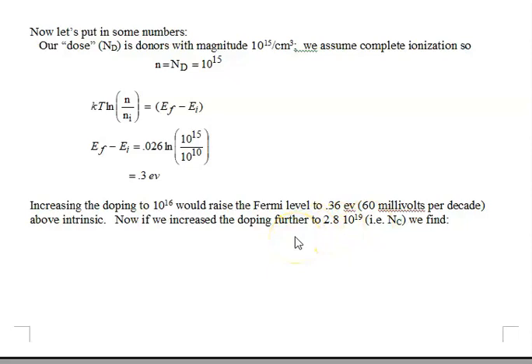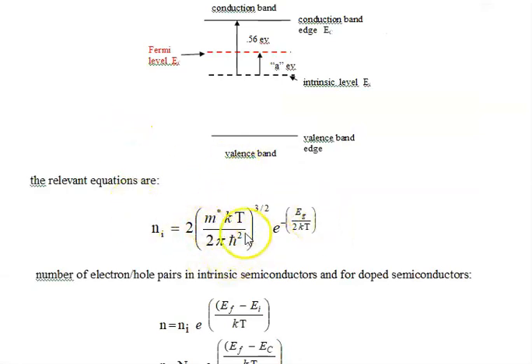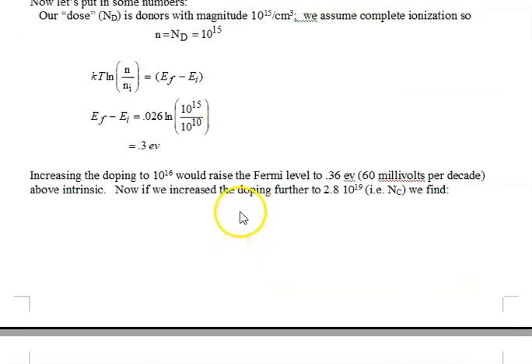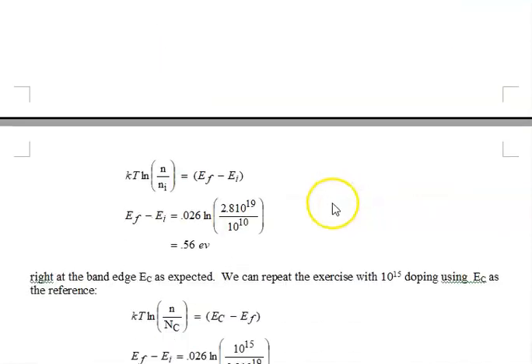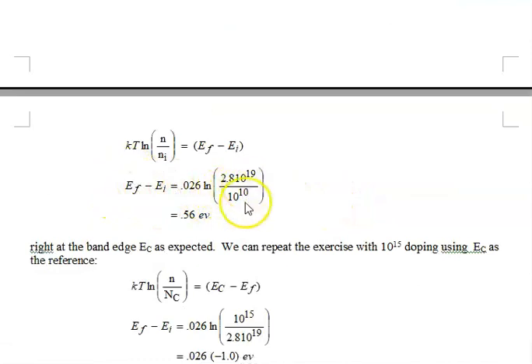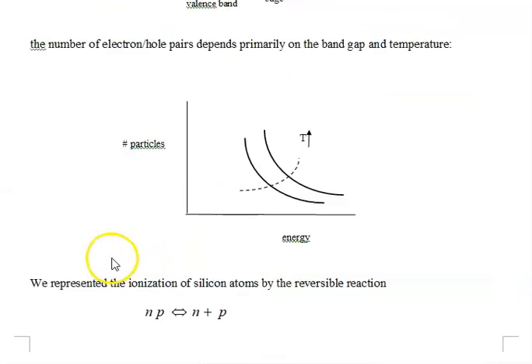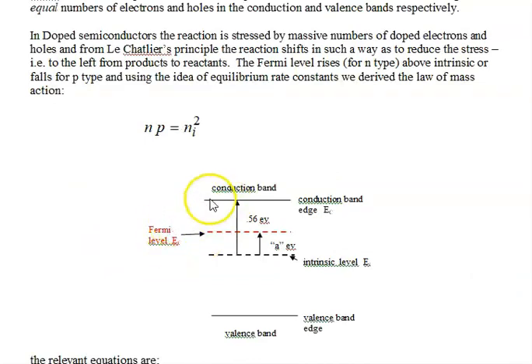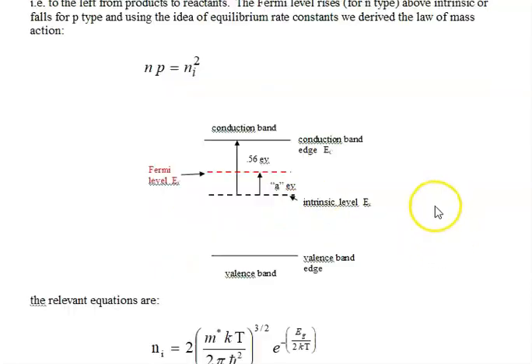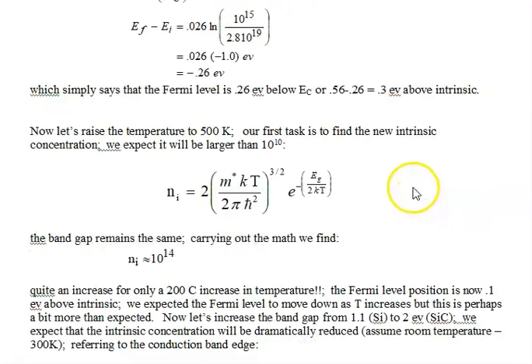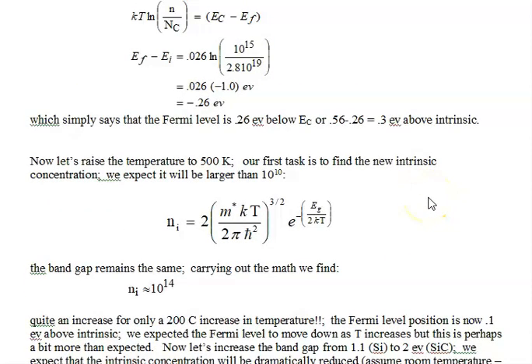Now, if we increase the doping, and I'm just kind of picking this out, actually not, sorry about that, this is a real number. This number right here, 2.8 times 10 to the 19th. If I would increase the number of donor atoms to 2.8 times 10 to the 19th, we would find, well, here it is, 0.56. So what happens here is, if we increase the doping way, way up, the Fermi level is now right at the conduction band. And that is a very important value, and we'll be using that quite a bit in coming sessions.